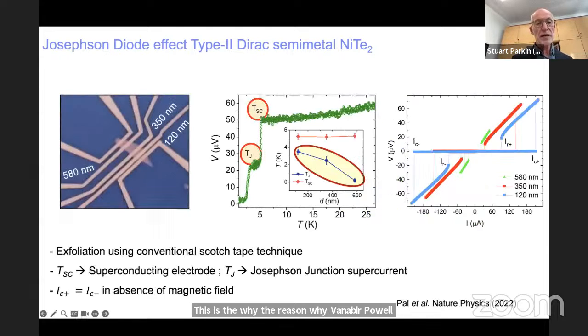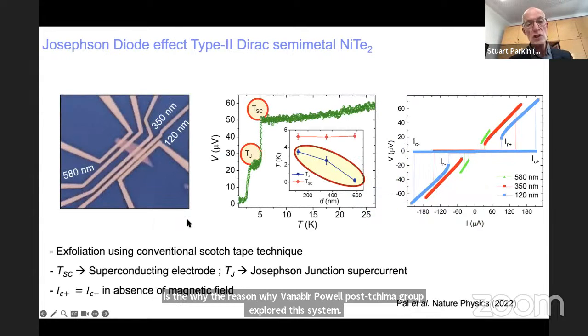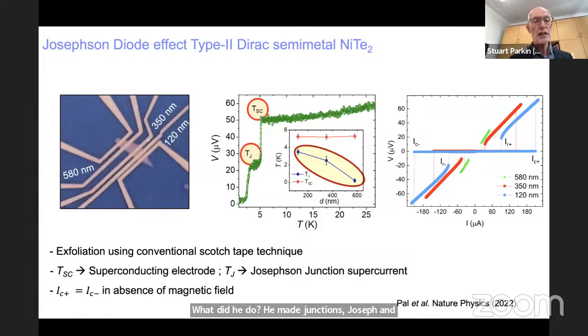And what did he do? He made junctions, Josephson junctions, just like the junctions I showed you with the chiral antiferromagnet. They were made with thin films. Here we exfoliate a flake shown on the left-hand side in this image. You can see the flake, this irregularly shaped object, formed from a thin layer of nickel ditelluride, exfoliated from a single crystal. And then the orange lines are conducting lines of niobium formed by electron beam lithographic techniques, separated by 120, 350, and 580 nanometers, all on the same flake.